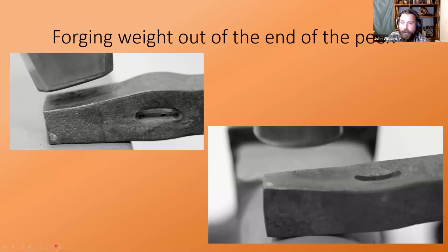All right. And often, I should say, very often I don't heat treat it at all. For these punches, I often will just do a little bit of a water quench on the end, but most of my chrome moly steel punches and drifts have no heat treatment whatsoever. I rely on having good technique to keep my business end from becoming affected by heat.